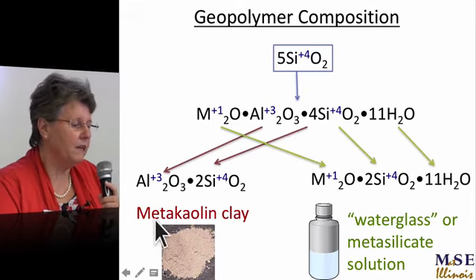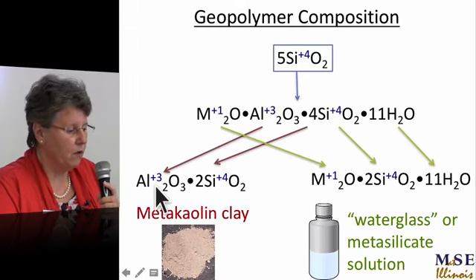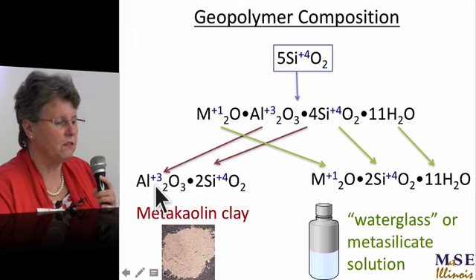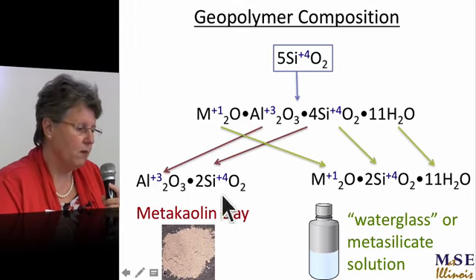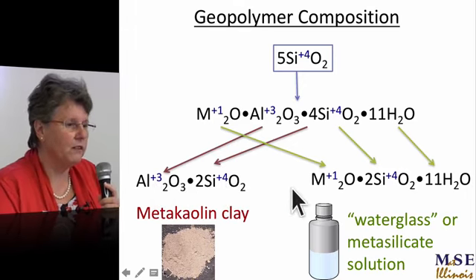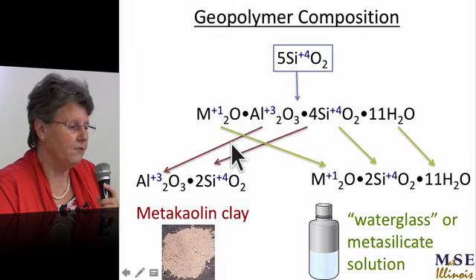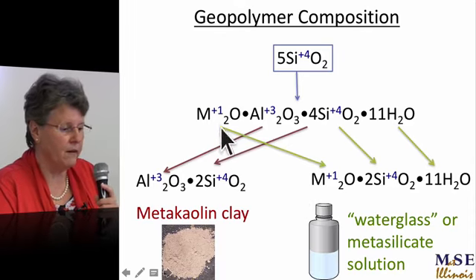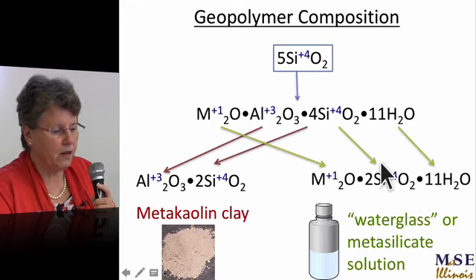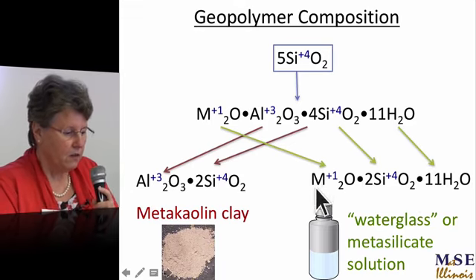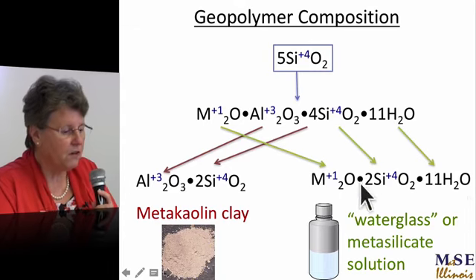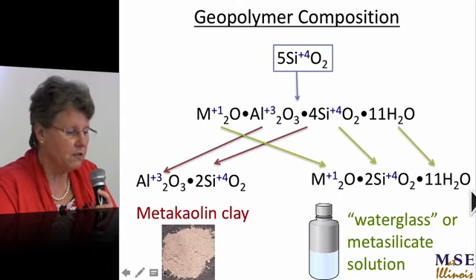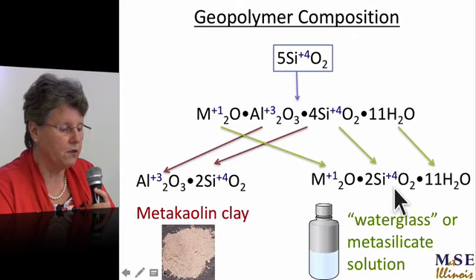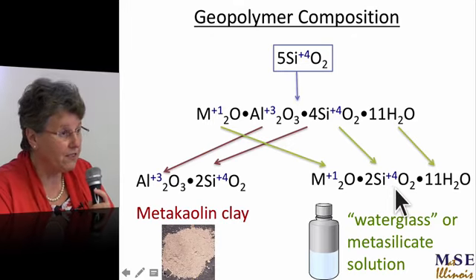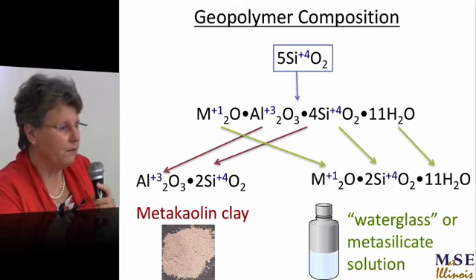And when you heat clay, it'll become metakaolin, and it'll be like a ceramic engineer writes. That's what I teach at Illinois. 1 mole of alumina and 2 moles of silica, and the water's gone. You know, if you heat it to 750 C for 1 hour. But the other ingredients come as you take, say, sodium hydroxide, potassium hydroxide, cesium hydroxide, and you dissolve in 2 moles of amorphous silica. And that could be from